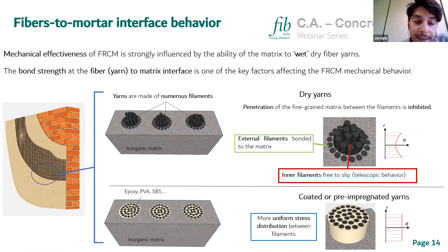So the yarns are usually dry, so the filaments are bonded to the mortar only on the external part of the yarn. The penetration of the matrix between the filaments is not possible because of the dimensions of the particles. And so only the external filaments are bonded to the matrix, while the inner filaments are free to slip, with what is called the telescopic behavior. And so the stress within the yarn is not uniform. We have higher stress on the sleeve filaments, while the inner filaments are free to slip with a very low friction.